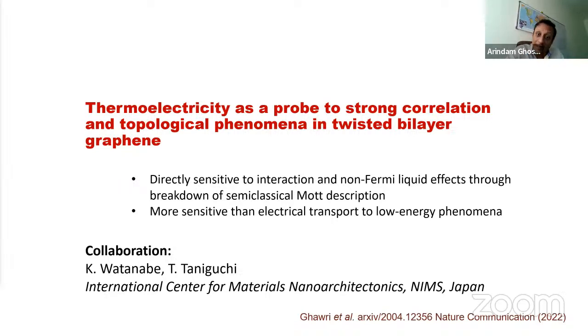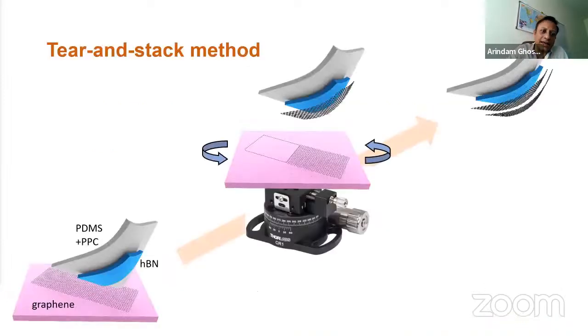Now, let me quickly tell you how to make these kinds of systems. They are not straightforward, because you are taking two graphene layers and rotating them by a very accurate angle of 1 degree or so and making a new system. This is called the tear and stack method. The way it's done is that you take a layer of graphene and a layer of boron nitride, and use the boron nitride to tear the graphene in half. The boron nitride takes the graphene out, and then you rotate it with respect to the lower graphene by the amount you want, and put it back on the graphene. And then you get a twisted bilayer graphene.